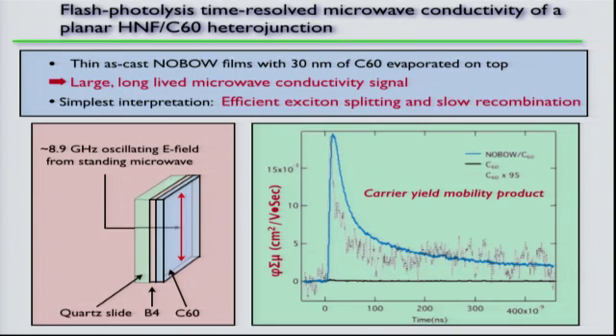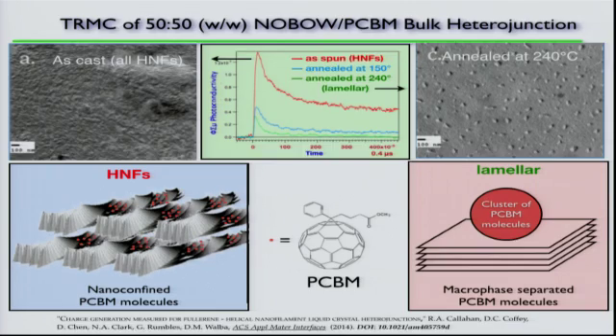Okay? So then we tried a bulk heterojunction like this. This is PCBM, solubilized fullerene. It's going in like this. I think it's kind of touching the layers, but I don't really know where it is. It's in there somewhere. You can't see it. And if you have the helical nanofilament phase, you get a pretty darn good signal in the time-resolved microwave conductivity experiment for this stuff, meaning it's good at splitting excitons.